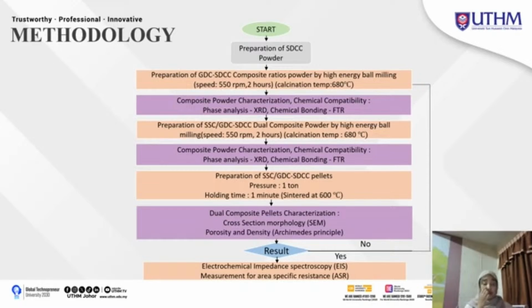And it is different because there will be temperature in dry and wet air, in the range of 500 degrees Celsius to 800 degrees Celsius. And if it's a yes, then like I said before, it will go through EIS, ASR. If it's a no, then I'll have to repeat the same steps from the early stage. So that's it.